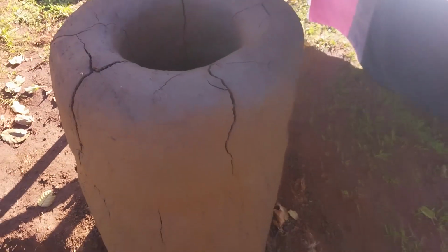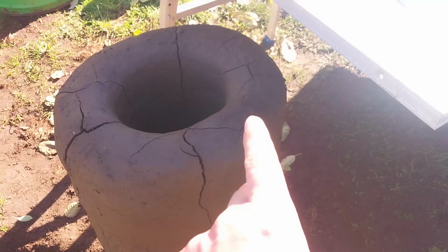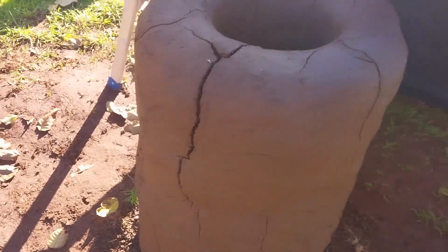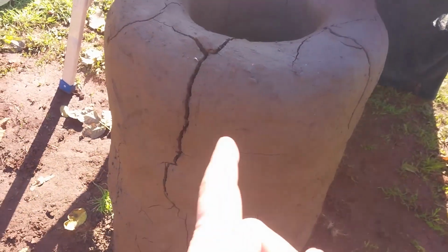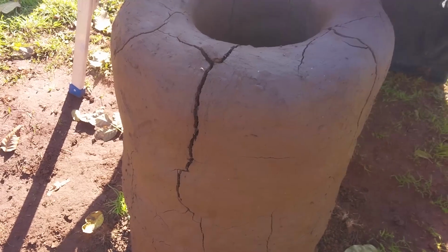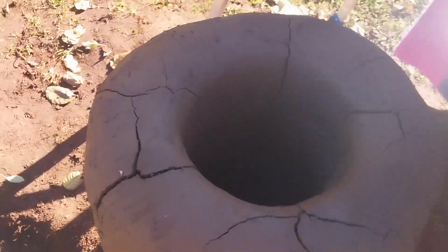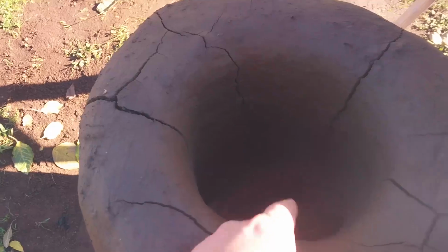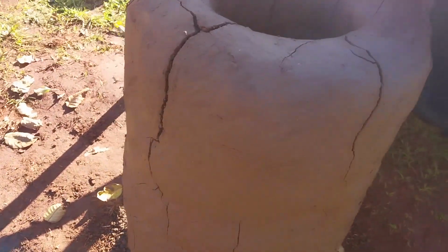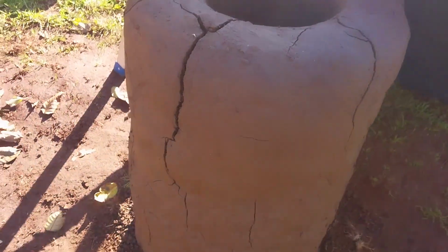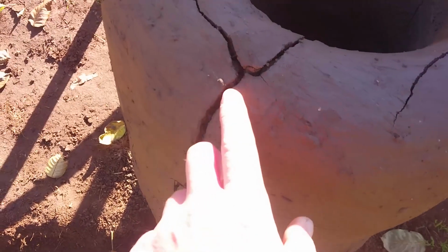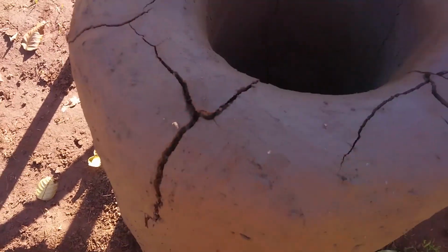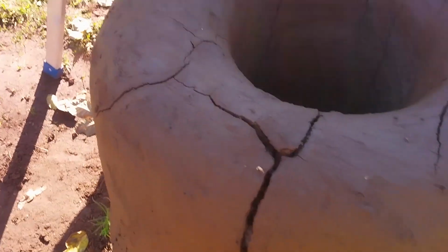So the cracks that we mentioned last time have pretty much stabilized to where they're going to be, but this one in particular grew to be about 5 millimeters across, which is, it actually stops just inside here, so it doesn't go all the way through, which is really good news, and it means that it's not catastrophic. And also the edges are still very, very clean and not crumbly, which is also very good. But you can see why they're happening if the sun is going to let me focus.